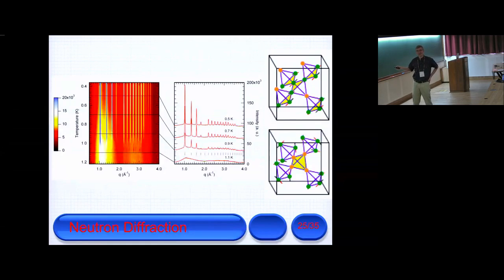You then think, well, let's go to a single crystal. That would be brilliant. And then you remember that there's domains. So if you have multiple domains, you're not exactly a powder average, but you've got some averaging. So we tried that, it didn't work. We still had many answers. So, as I'll show, we've tried several other things. But from diffraction alone, we can speculate, or if we were really honest in a 10-page paper, we could show you 10 different models and say it's one of these. We often have to sort of point to something, and we'll use other probes to try and get it correct.